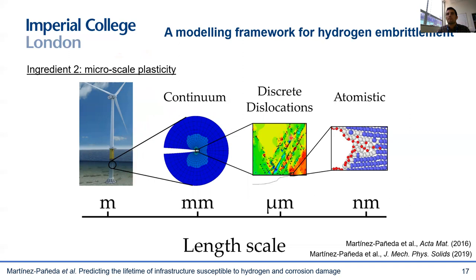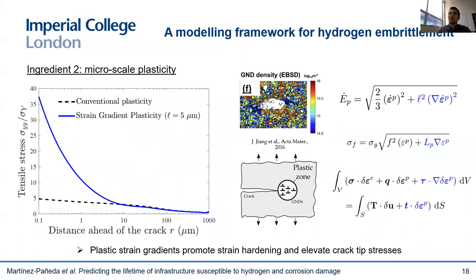So we can enrich continuum models with the physical effects that are missing at the critical distance, which basically introduces the physics implicitly by changing the constitutive equations. At a few microns ahead of the crack, the main effect that conventional continuum plasticity models are missing is the dislocation hardening associated with geometrically necessary dislocations (GNDs). So we have developed new multi-scale plasticity models — so-called strain gradient plasticity models — that can capture those dislocation hardening effects and the stress elevation associated with them. You can see here the tensile stress ahead of the crack tip as a function of distance for both a conventional plasticity model and a strain gradient plasticity model. As we approach the crack tip, GNDs and plastic strain gradients start playing a role and significant differences are observed.